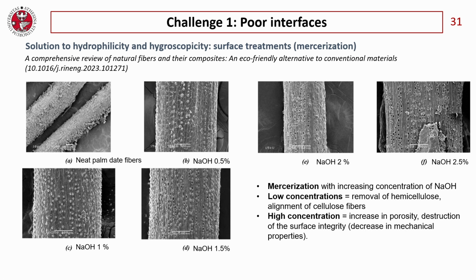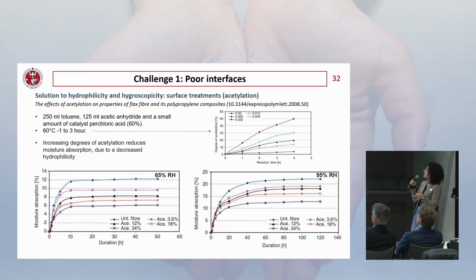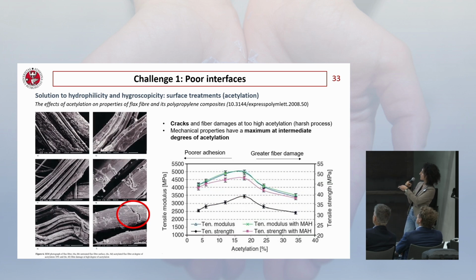But if you use too much NaOH, what happens is that you basically fill the fiber surface with defects, and this will decrease their mechanical properties. So a little bit is okay, too much is not. The same is true for acetylation, for example. Here you can see how acetylation contributes to decrease the water absorption of these kinds of fibers. But if you use too much, so the acetylation treatment is too harsh, you will eventually decrease the mechanical properties, the tensile modulus of both the fibers and also the final composite.